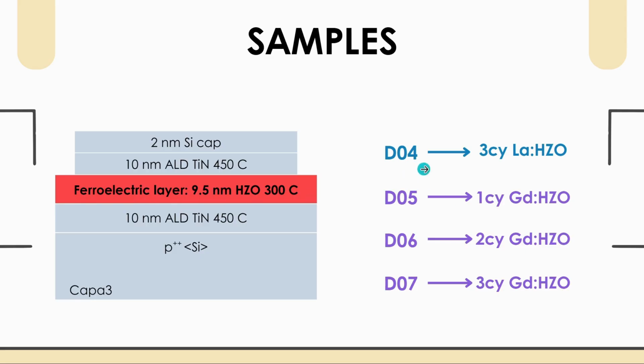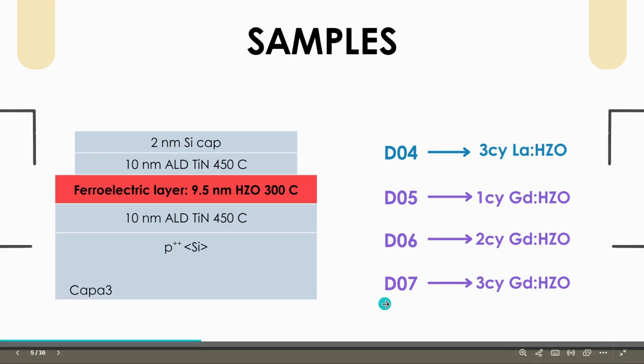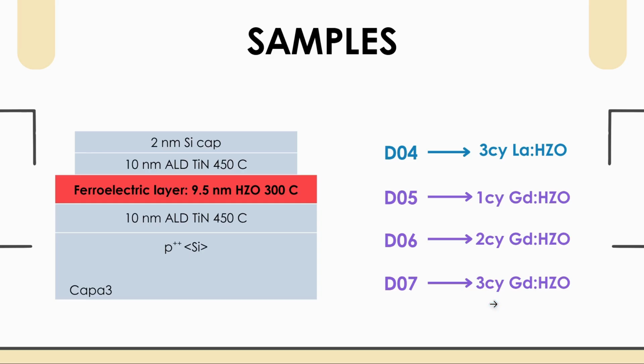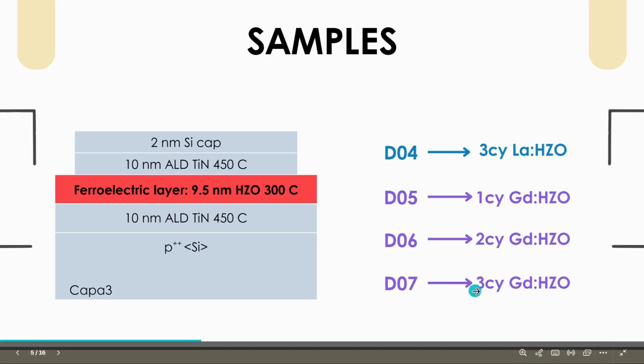For DO4, we used 3 cycles of lanthanum doping. For DO5, we used 1 cycle of gadolinium doping. DO6 uses 2 cycles of gadolinium, and lastly DO7 has the most gadolinium doping with 3 cycles. These doping cycles control how much lanthanum or gadolinium is inserted into the hafnium zirconium oxide film.